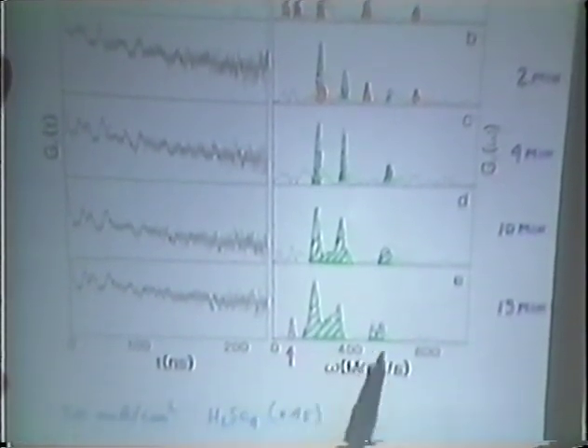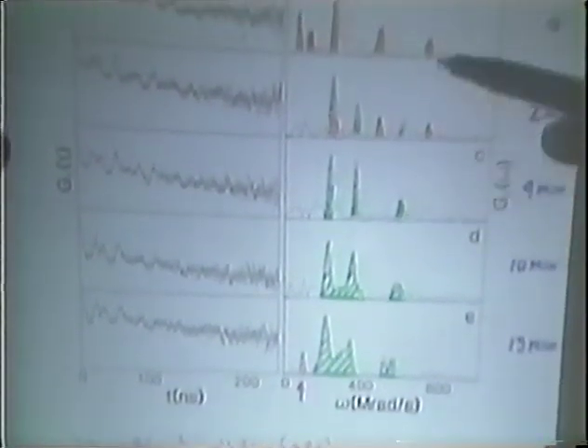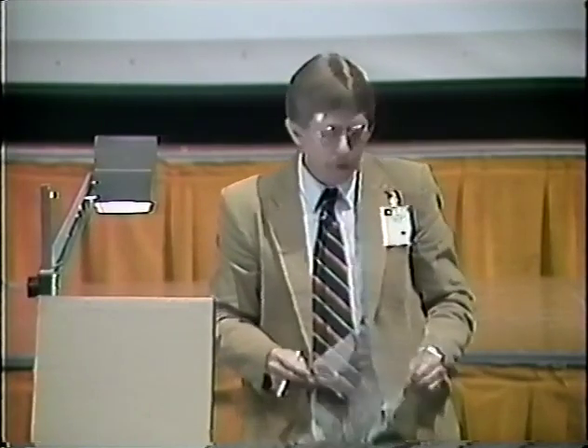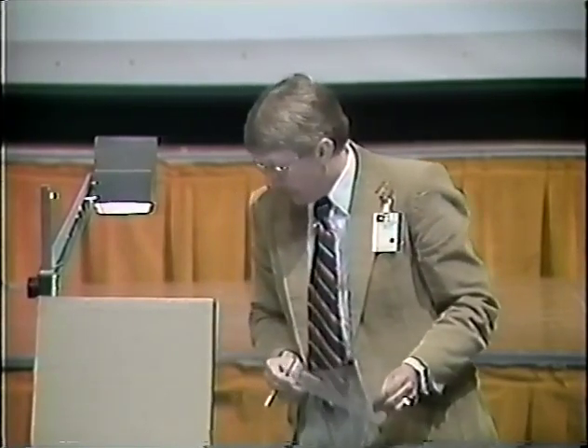After 10 minutes and 15 minutes, you get a broadening and smearing of the frequency distribution. We attribute the shift from here to there to trapping of a single hydrogen atom, and then the subsequent broadening to trapping of multiple hydrogen atoms. So it's very easy to introduce hydrogen into the lattice. It traps relatively strongly in these vacancy complexes with binding enthalpies of the order of half an electron volt. And we can also observe multiple trapping.